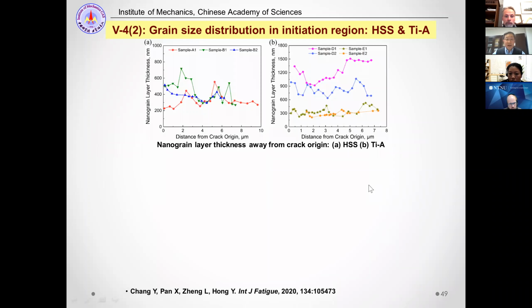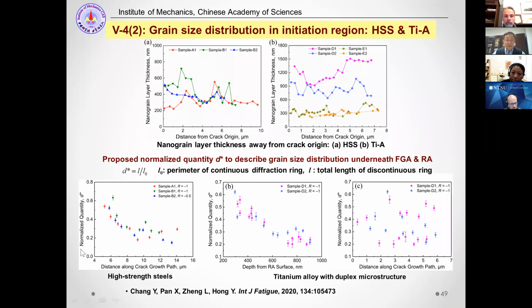We are also able to measure the thickness of the nanograin layer for high strength steels and titanium alloys. We also propose a normalized quantity, D star, which is L over L0. L0 is the perimeter of the continuous diffraction ring, and L is the total length of this continuous ring.